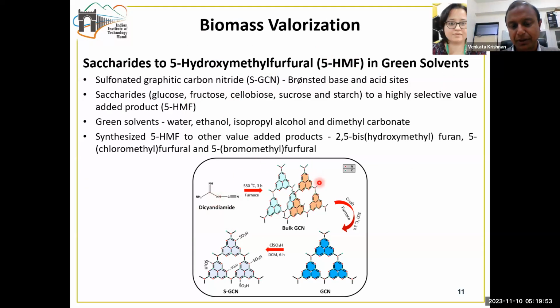From this precursor, we prepared the graphitic carbon nitride, and then subsequently we prepared the bulk graphitic carbon nitride, and then we prepared the layered structure of nanosheets type of graphitic carbon nitride, and then using chlorosulfonic acid treatment, we have incorporated the sulfonic acid groups onto this graphitic carbon nitride. The beauty about this sulfonated graphitic carbon nitride is it has both Bronsted base and Bronsted acid sites. The Bronsted acid sites come from the sulfonyl group, which is used for the functionalization, and the Bronsted base groups come from the nitrogen, which is present in the backbone of this graphitic carbon nitride.